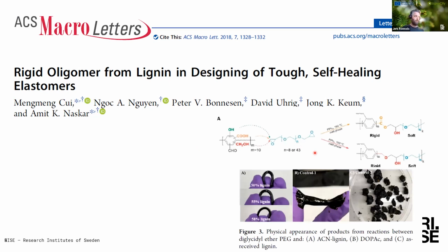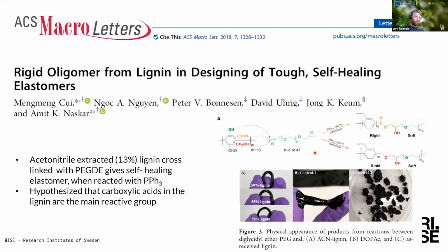So these are pictures from their paper, this one. And they say that it's both elastic and that it's self-healing, which is two very interesting properties, and also that it's bio-based. One drawback from their method was that they used only a subset of the lignin. They made an extraction with acetonitrile to get 13% of the lignin, which they then cross-linked. And they hypothesized, or they of course tried with the whole lignin, but they hypothesized that the increase of carboxylic acid groups in this extract gave it beneficial properties in the cross-linking.